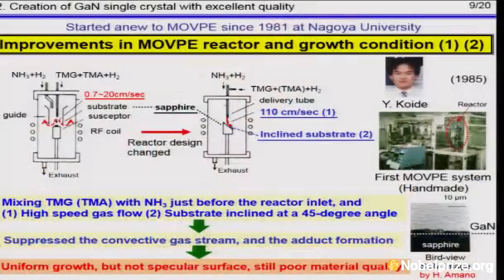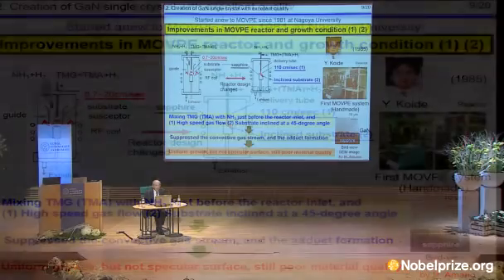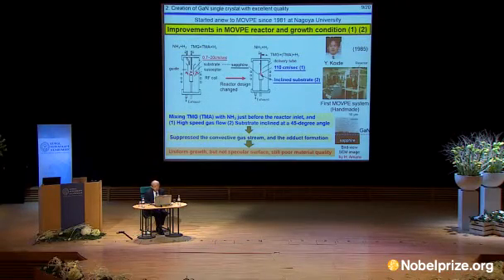First, Koide increased drastically the flow rate of the mixture of organometallic gases and hydrogen gas to about 110 centimeters per second from the previously only 2 centimeters per second. And he also blew the gas onto the substrate inclined at about 45-degree angle rather than placed horizontally as in the previous attempt. We were thus able to suppress convective gas streams on the heated substrate and make the gas flow smooth to achieve the uniform films.